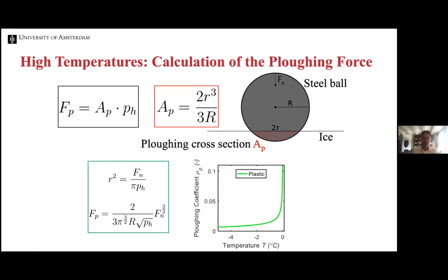And so plowing friction is something we can actually understand quantitatively. So the plowing force is the area created by the sphere plowing through the ice. So it's really the plowing area times something called the penetration hardness, which is the plastic modulus of the ice. And so if you know now how deep the sphere goes into the ice, then you can calculate the plowing force. And if you know the penetration hardness, you actually do know how deep the sphere goes into the ice. And so if you do that, you can immediately calculate the plowing force and retrieve, if you like, the 3/2 power that we found in the experiment.